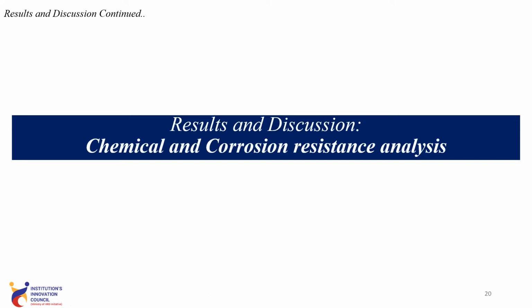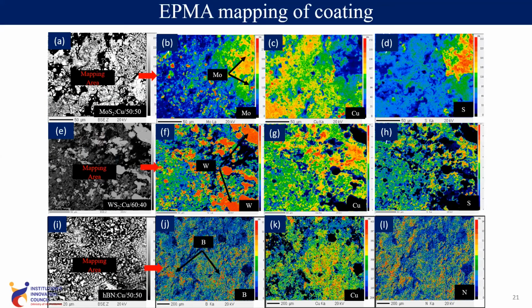Now we discuss the chemical and corrosion resistance, and we do the chemical and corrosion resistance analysis. So we have performed the EPMA mapping that is used to denote the spatial distribution of the coating elements, that is Mo, copper, sulfur. These images are for E, F, G for WS2 copper, and I, J, K, L for HBN copper. In these images, we observed that there is a uniform deposition of the metal on the workpiece surface. The dark orange part shows the Mo, copper, S. Similarly, the dark orange part shows the tungsten, copper, sulfur, and boron, copper, and nitrogen. So we can say that there is a uniform deposition of the tool material on the workpiece surface.